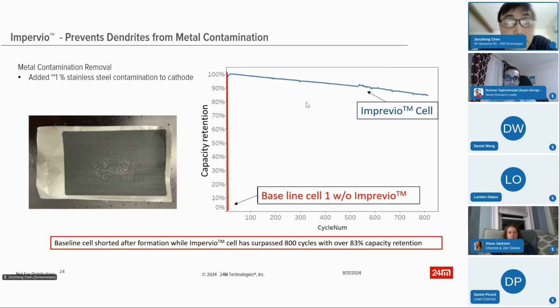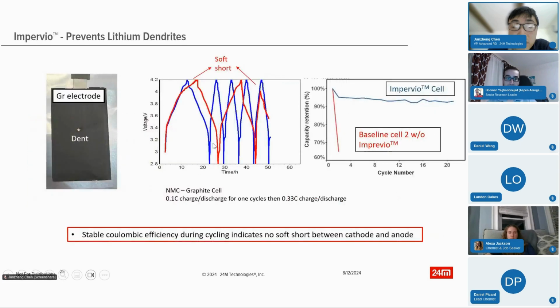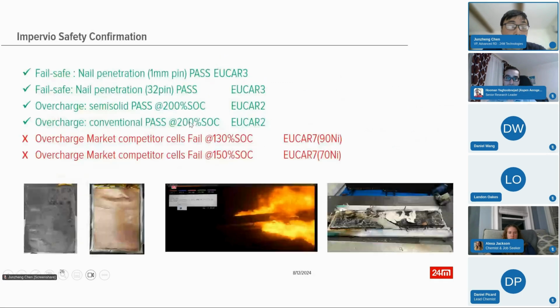The first dendrite we're introducing is a metal dendrite during the manufacturing. This metal dendrite during the manufacturing has lots of powders, and it shorts right away, but this one can demonstrate long cycle life. And then we have the defect cells with dendrite growth. It shorts right away at the beginning, but with this Impervio, you can block the lithium metal growth through the separator at all.